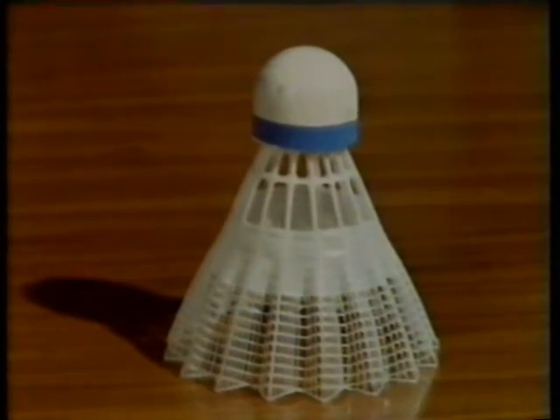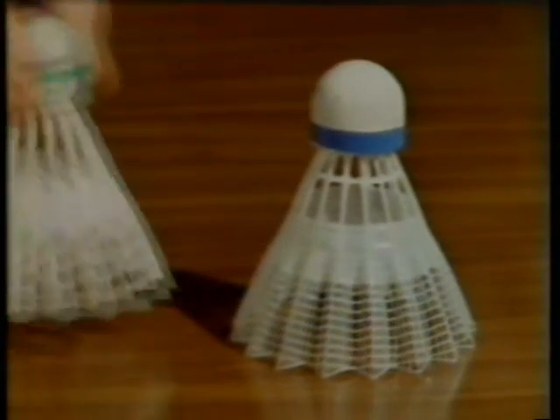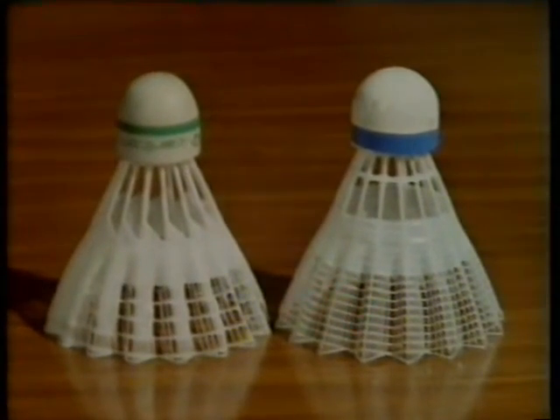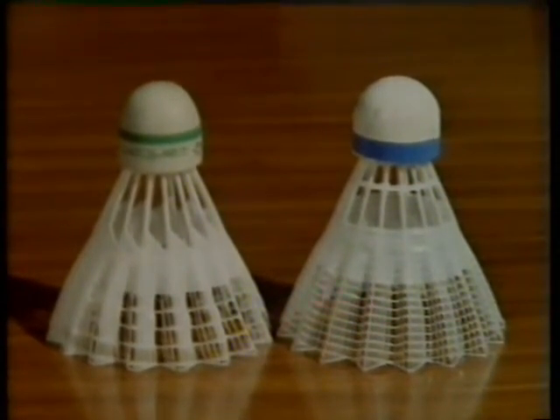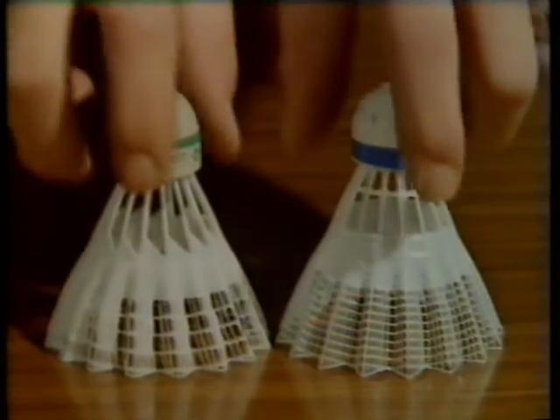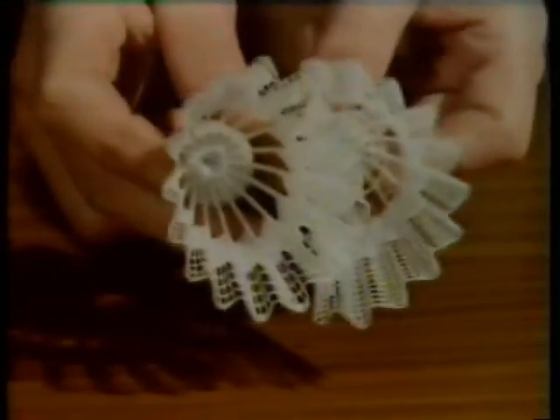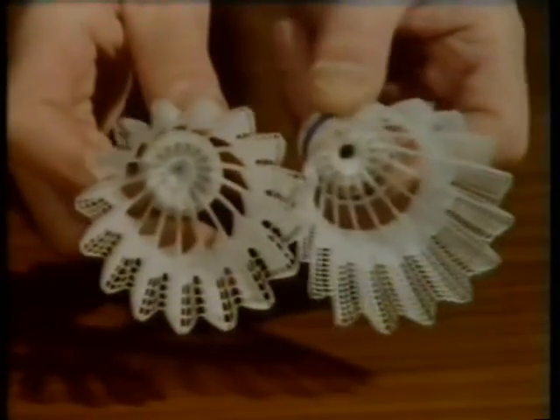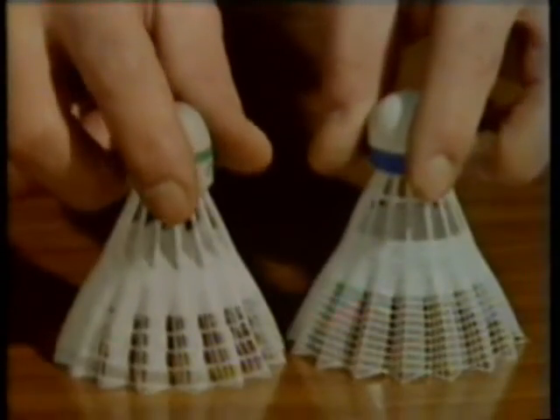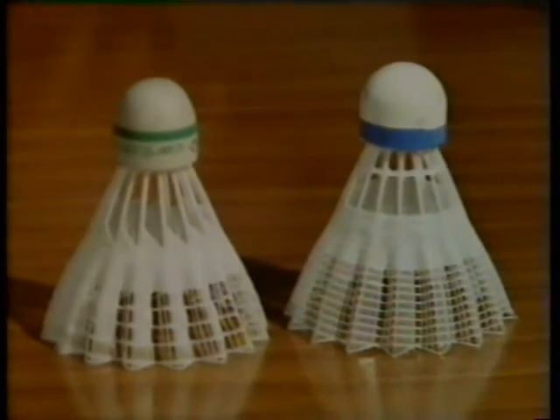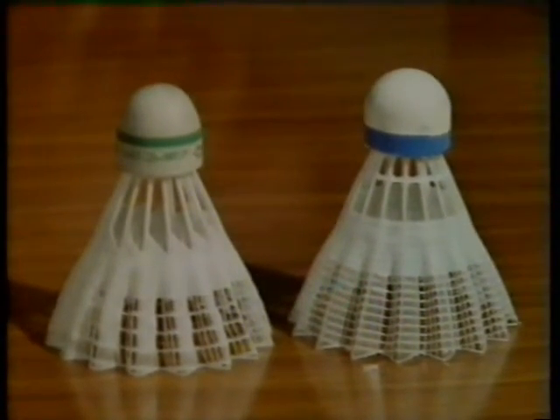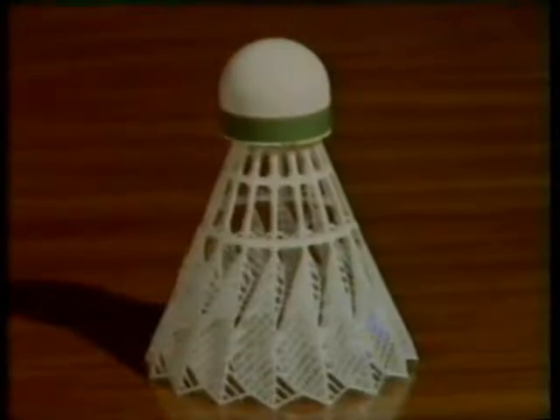But designers are always looking for improvements and better solutions, and this shuttle is still not stiff enough. So they tried a new shape and a new material, nylon 12. The combination of the new shape and the new material produced a stiffer skirt. But new solutions produced new problems. Although it was stiffer, nylon 12 turned out to be not as durable as nylon 11. So if you have two materials with properties you need.